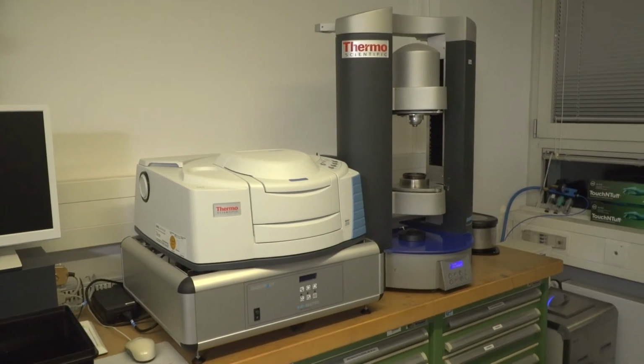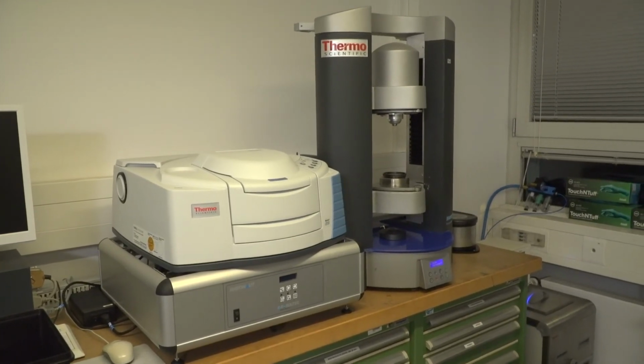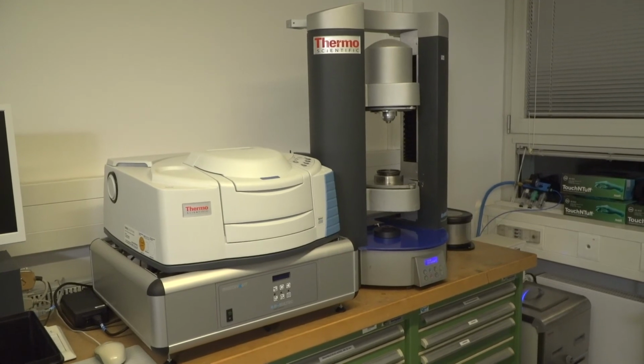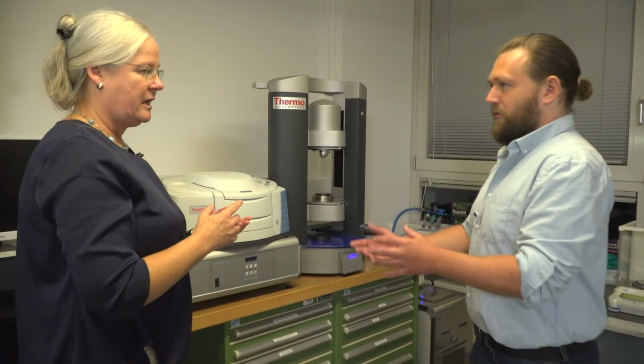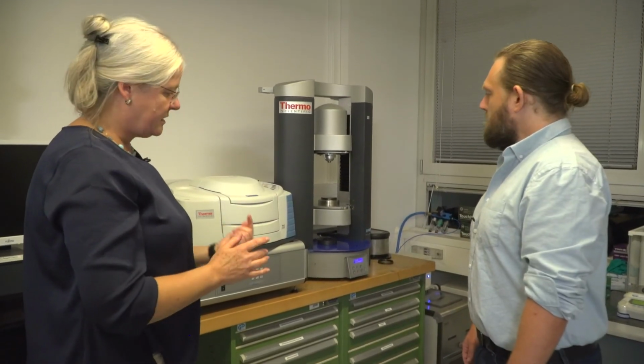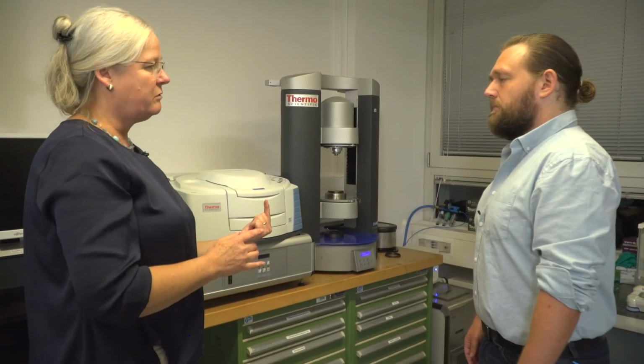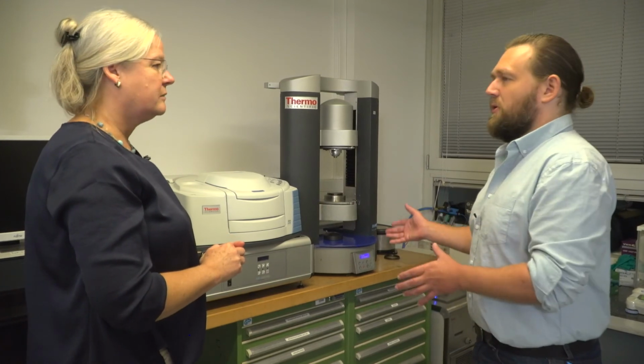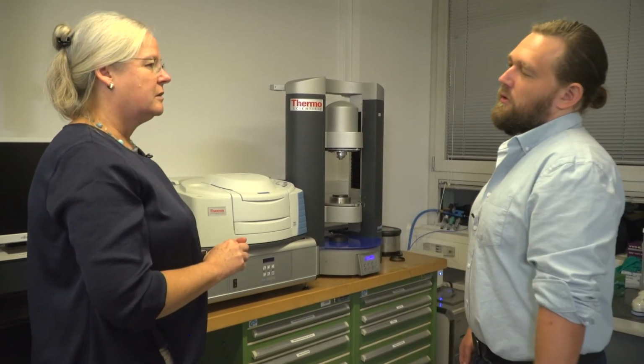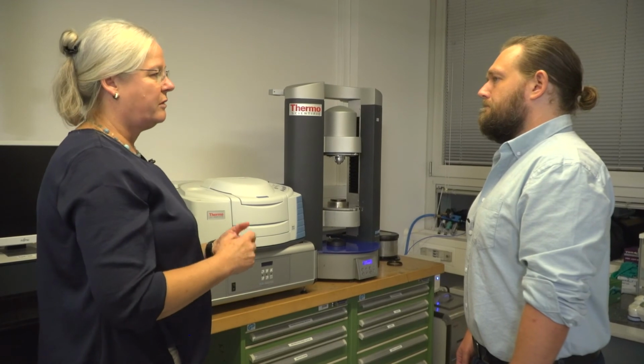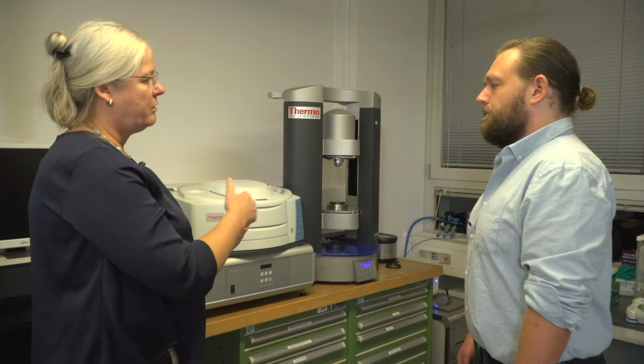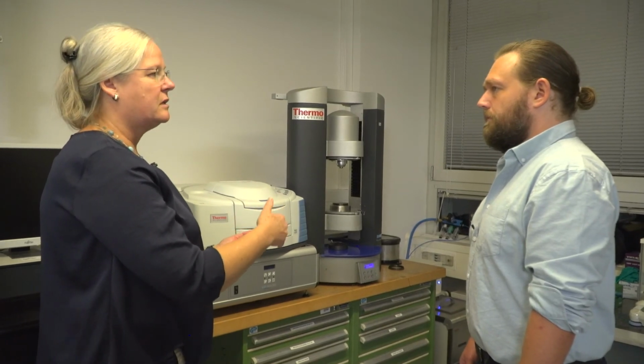What does this system over here do? This is a rheometer where we measure the viscosity during the sol-gel process. So you can watch your liquid get more and more viscous until it gels. In addition, it has an analyzer for the composition via FTIR. What kind of information do you get out of this? We need the information of the bonding in the system, and you see how the sol-gel process progresses.